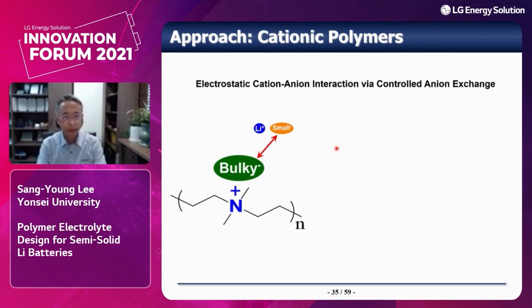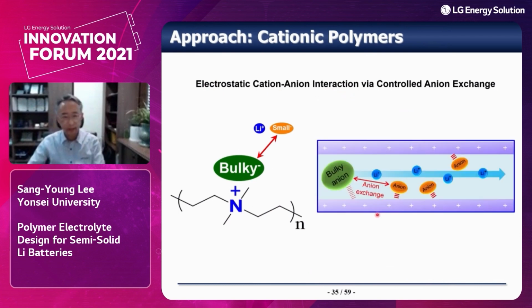Our approach is the cationic polymer-based one. We have synthesized quaternary ammonium-based cationic polymers coupled with bulky anions. When we add the electrolytes containing the lithium salt, which contains small-sized anions, they can exchange. So we expect electrostatic cation-anion interaction. We control the anion exchange reaction, and eventually we expect this gain.